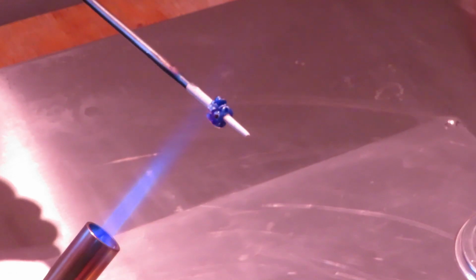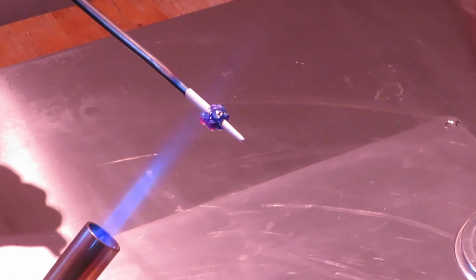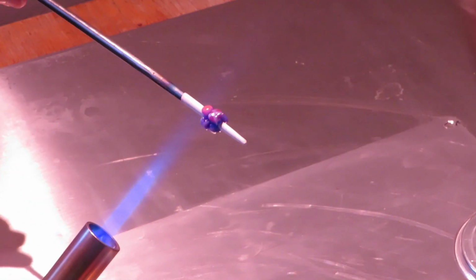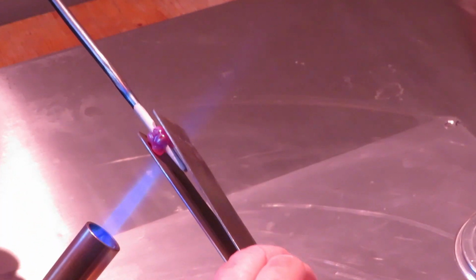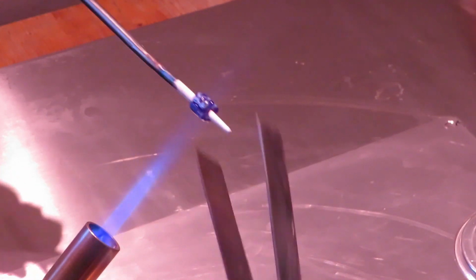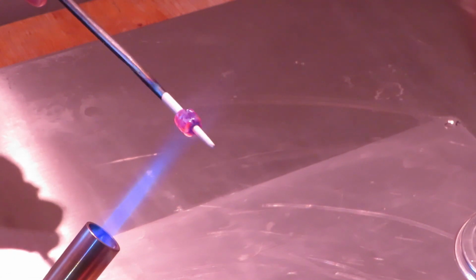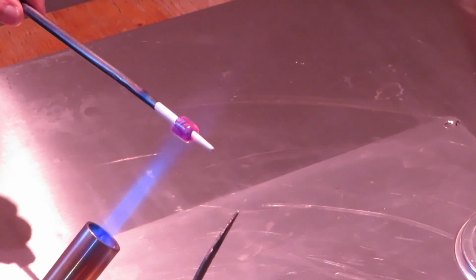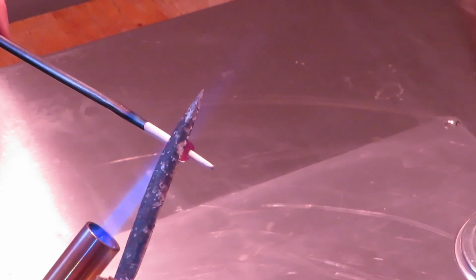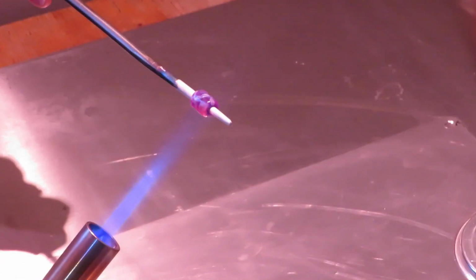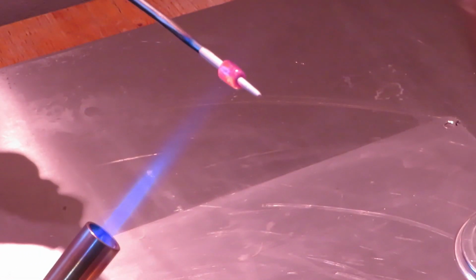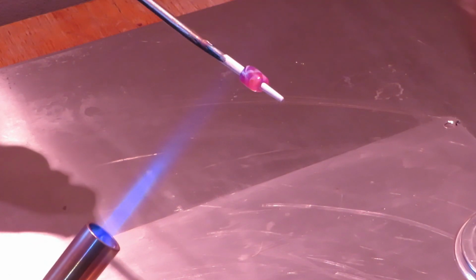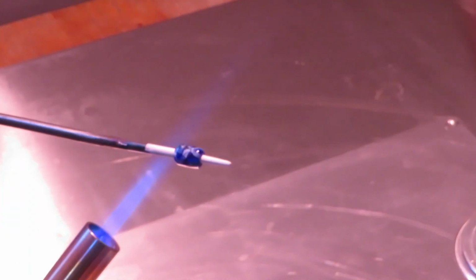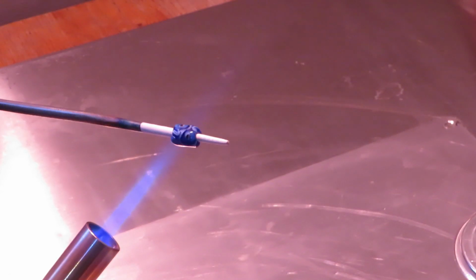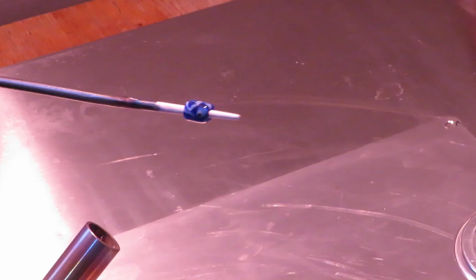Cane slices in place, a total of 8 different slices, 4 from each pattern, alternating around the bead. Now tonging to consolidate, and as the heating continues, the cane slices move to fill the gaps between them. Now I'm removing it from the flame to cool. And here it is, the finished bead, ready to be pushed into vermiculite or sand to cool down.